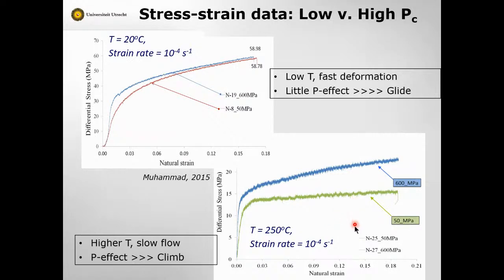So we definitely see evidence for different processes: glide at the lower temperatures of fast deformation, and climb controlling the rate of creep at higher temperatures or much lower strain rates, like you'd expect in slow deformation around cavities in the long term or in nature. Okay. The interesting thing is, this is also reflected in the microscopic structure of the salt.